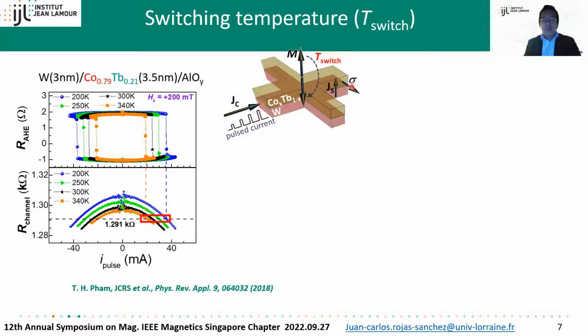Here, for example, we have a schematic of our Hall bar. We have tungsten, cobalt terbium, and aluminum: just 3 nanometers of tungsten, 3.5 of cobalt terbium with magnetization perpendicular to the film plane. When we inject current, eventually with a little in-plane field, we can switch this magnetization. But what we found surprising is that, independently of the initial temperature, the device reaches the same temperature, and we can observe that here on the left.